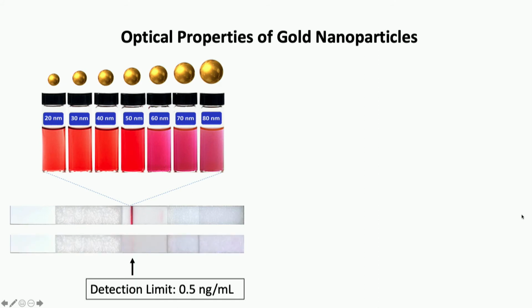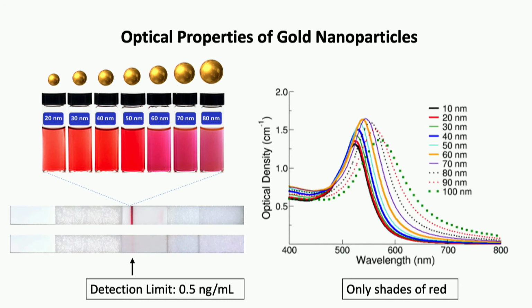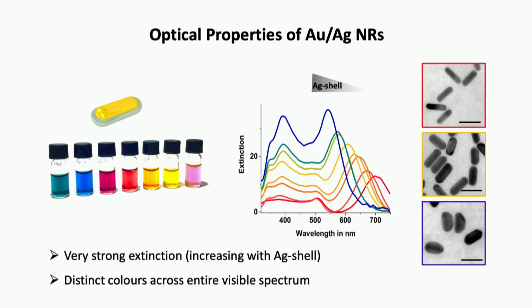And no matter which size of sphere you use, no matter what you do, the detection limit is 0.5 nanograms per milliliter, which is quite high if you want to detect early viral infections. And another thing is you're limited to a red color, because no matter what, the gold nanoparticles only have shades of red. So these gold-silver core shell nanorods that we have now, you can see here beautifully, cross the entire visible spectrum, and as you can see in this graph, have really, really strong extinction. The thicker the silver shell, the more the color is shifted towards the blue, the stronger the optical response.